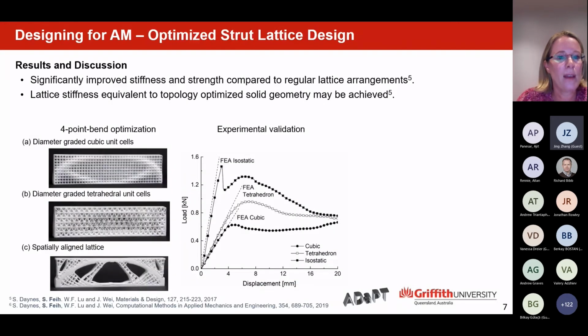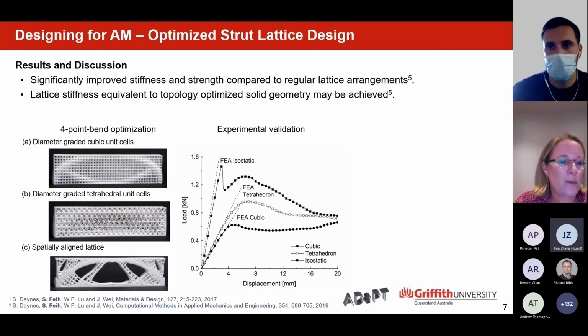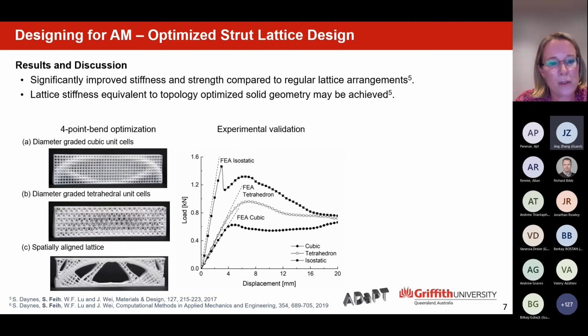Now, I also want to highlight quickly some work by Stephen Daynes, my colleague at Simtech, on optimized strut lattice design. So we saw a couple of things earlier that Ajit showed. We've done a lot of work trying to figure out how general lattice structures with very uniform cells perform against spatially aligned lattices, which is what we see in nature. And we could actually show with our patented algorithms that we can come up with spatially aligned lattice structures. This is based on the strain field, and we align the truss elements with the principal strain directions.